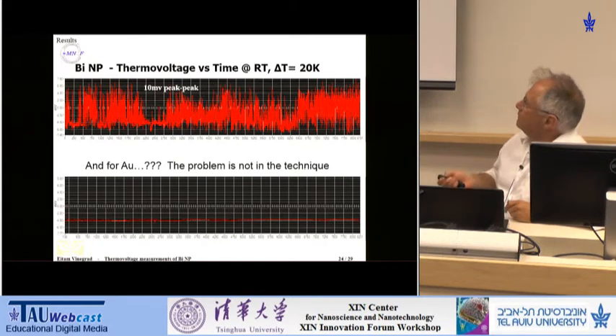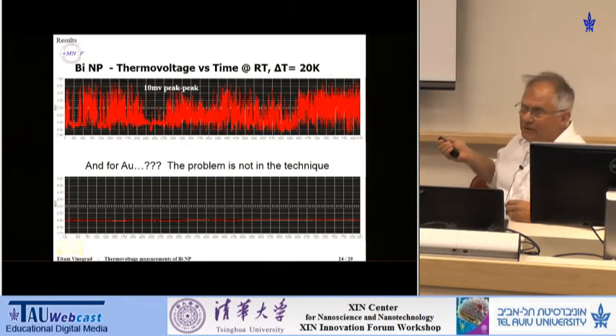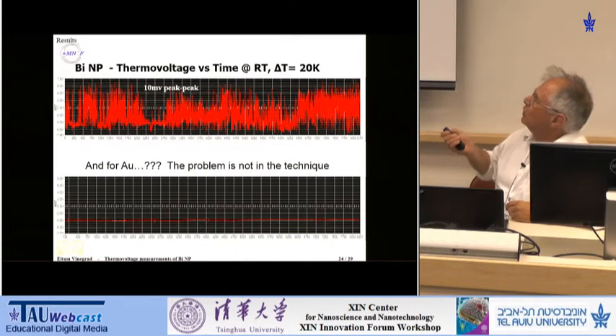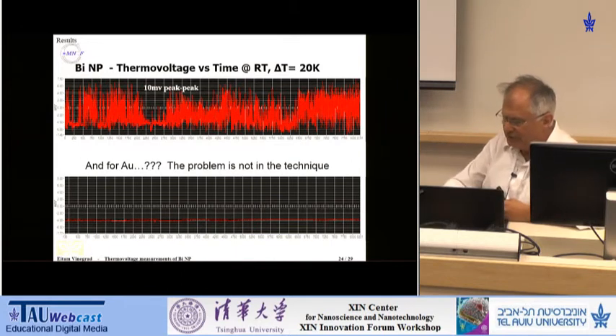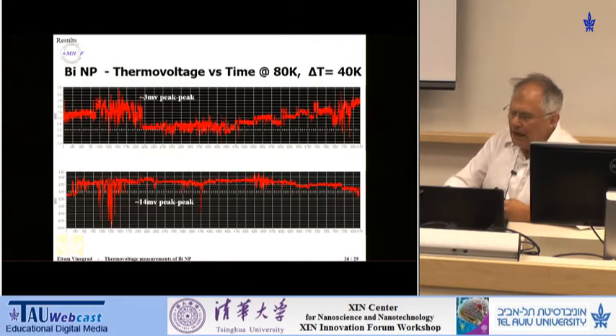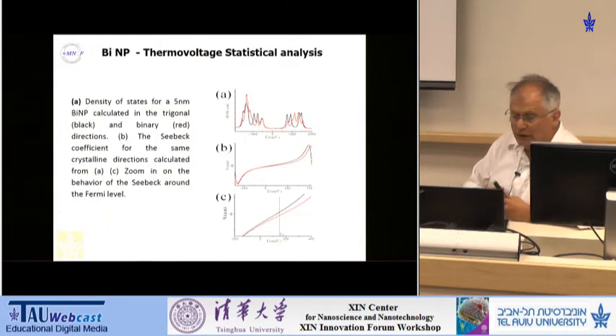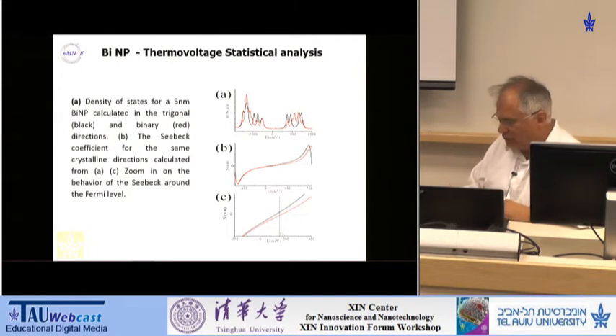And again, if you compare the same measurement over a very long period of time, you see, yes, we know how to do these measurements. We get very reasonable value, very stable value that do not change in time, while the bismuth nanoparticle is still very erratic. I will not dwell much time on the details. I would like just to tell you we were quite disappointed and quite frustrated to see that. And then we have decided to do theory and to see what do we really see.